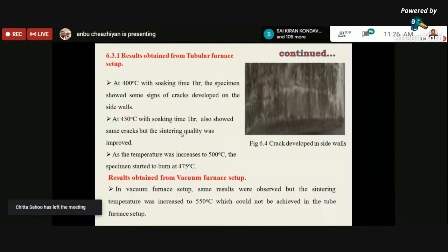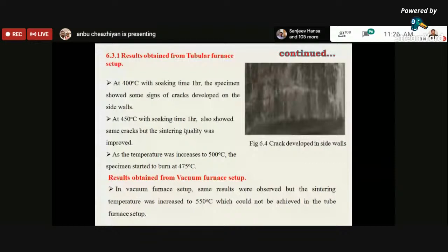By increasing the temperature from 400 to 450 degrees centigrade, it showed the same cracks on the surface of the material. Then we decided to go for 500 degrees centigrade. When we increased the temperature further, the material started burning, so we were not able to get the composite. That is what we obtained in the tubular furnace setup. After that, we decided to go for the vacuum furnace, thinking about what would happen if we increased the temperature.